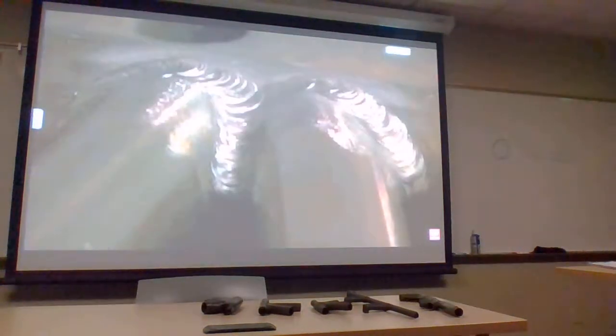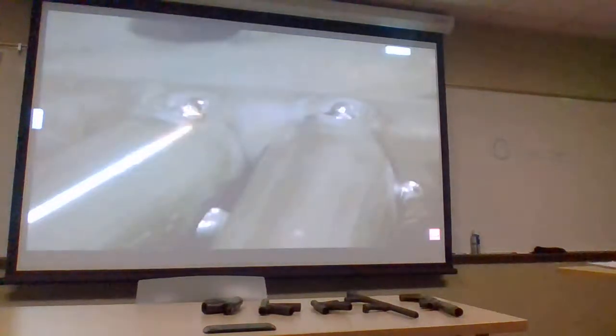So sometimes on 4130 chromoly tubing, there will be times when you need to weld it and it's not clean down to shiny bright metal. Not the end of the world. It's just going to weld a whole lot better if it is clean. See, that was shiny bright metal, nice weld. Same joint, almost identical, no cleaning at all. Watch the puddle here. It's maybe slightly more sluggish than with the completely clean metal, but still not bad. It's still flowing. Not a terrible amount of oxide islands floating around in the puddle or anything. Still going okay.